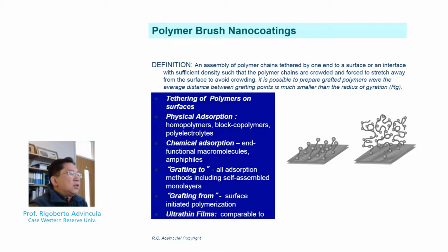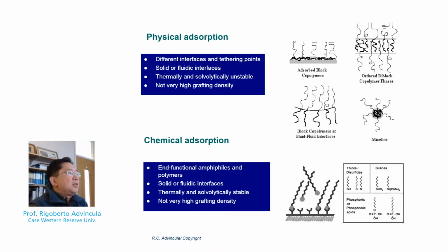Later on, I'm going to distinguish 3 other types of grafting methods: grafting from, grafting onto, and grafting through, which can have consequences on the density of a grafted polymer system on a surface. So what we label physical adsorption means that you have an interfacial boundary where a block of polymer or surfactant is distributed between this boundary of 2 phases. It can be achieved thermally or solvolytically. However, these are initially non-equilibrium phases, which then equilibrate over time.